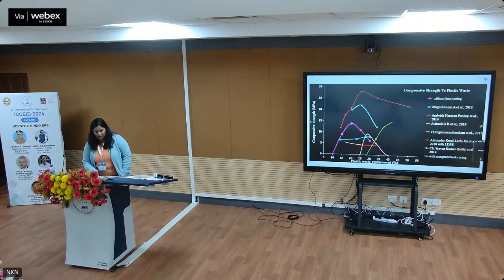This is the comparative study of the plastic waste replacement in different studies. These are the different studies. I have not incorporated my study into this because our study has completely replaced the binder with plastic waste by 100%. So we have obtained a strength of 22 megapascals with the heat curing.